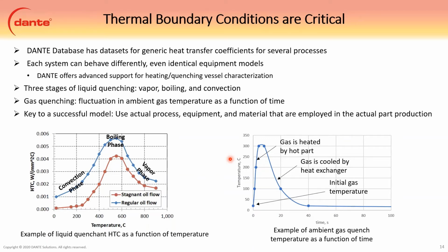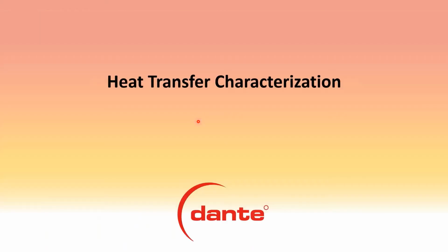However, the material testing for heat transfer is helpful. Stainless steel works really good also, austenitic stainless steel, because it doesn't go through a phase transformation. So there's no change in thermal properties. So a lot of times we'll use stainless steel, but these first two are absolutely critical, using the actual process and the actual equipment.